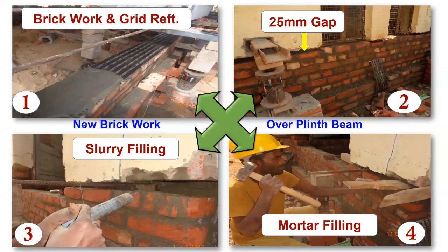We have interconnected them. The purpose is this. Previous cases of lifted buildings show a lot of signs of cracks because of minor settlements after the lifting process completes, after a year or two. That creates a lot of cracks in the building. To avoid that, we have used this kind of reinforcement. This reinforcement will take the tension force and will not allow cracks to happen in the building, or even if they happen, it will control the crack growth.